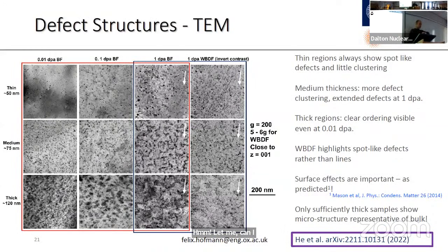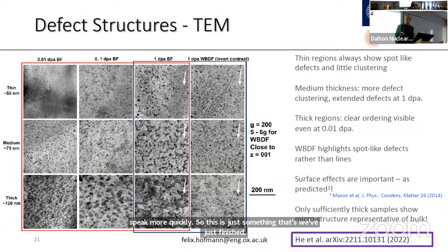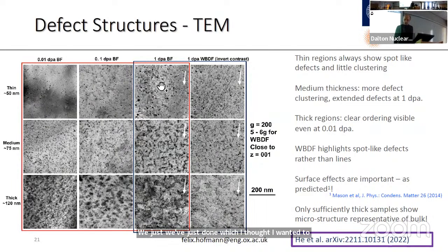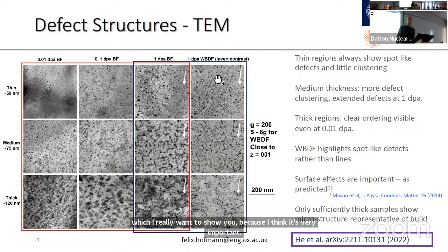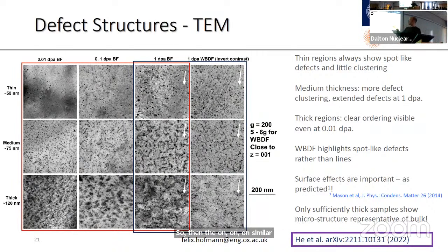Can I eat into your time by 4 minutes? I'll speak more quickly. So this is just something that we've just finished, which I really want to show because I think it's very important. So then on similar samples, irradiated to similar dose, the same material, slightly lower ion energy. So this is 2 MeV. We also did some TEM, and we looked specifically. So these samples were implanted and then back thinned, and we looked at different sample thicknesses.